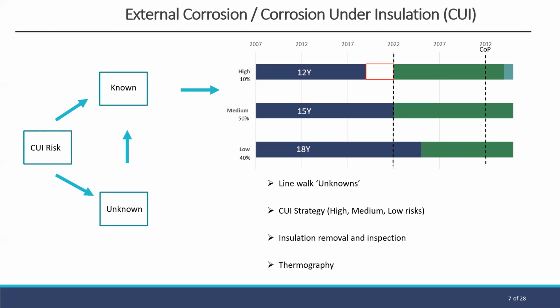are identified for high, medium, low risk items over the life of the asset. As you can see, our medium risk items are due this year. In addition, our high risk items were due to have insulation removed in 2019. So this is currently out of compliance. We had a glycol failure in 2020 and had a CUI strategy been applied and implemented, this could potentially have been prevented.